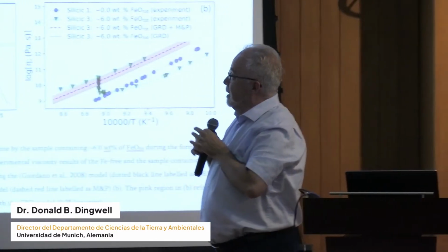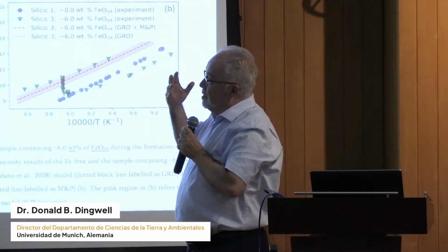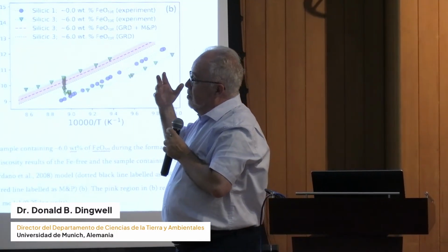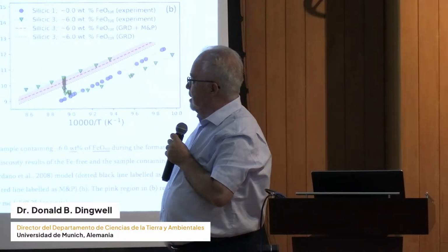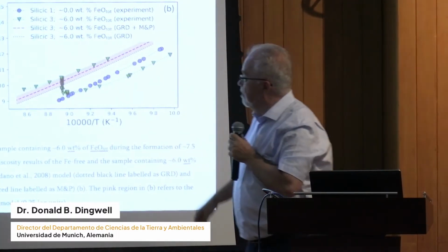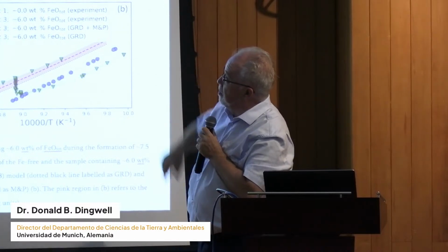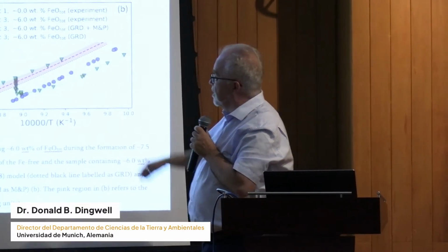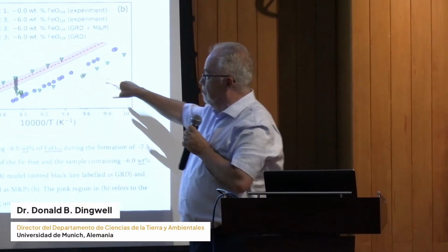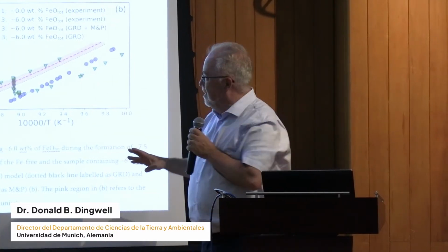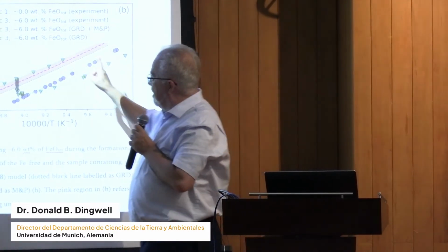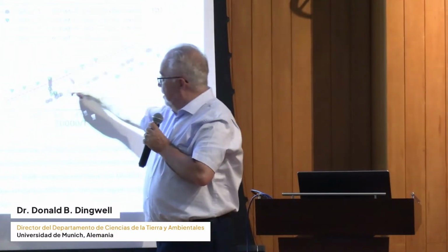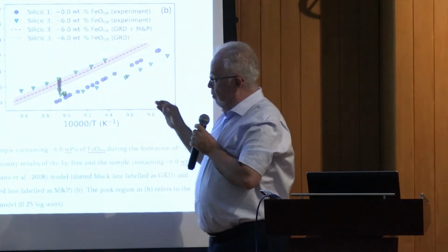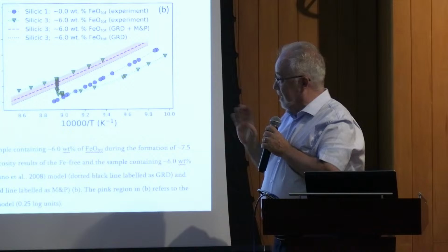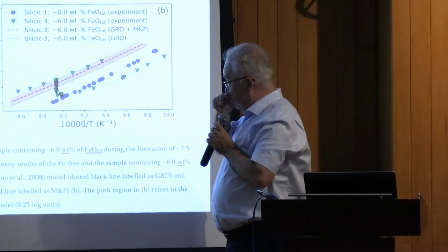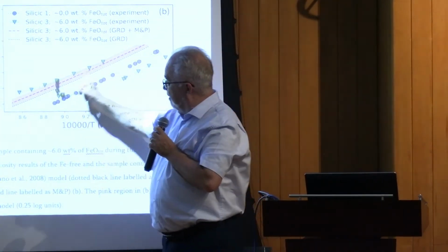So if you can create crystallization in these systems, then you might be able to see what the influence of crystallization is on the viscosity. So what we did here in a paper coordinated by Luis Pereira was actually a reanalysis of measurements that were 10 years old from Paris. And basically you have viscosity measurements of the system before, so they're nanolite free, and then the nanolites form, so before on the bottom and after on the top.